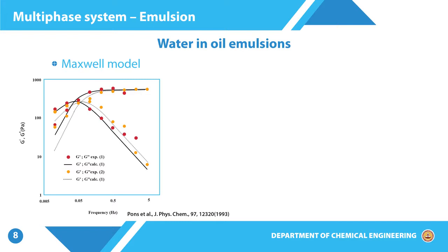In this case, frozen response means that basically droplets are unable to move. At most there is a small vibratory motion of the drops which is possible, and therefore, some amount of dissipation is there, but the overall cluster of drops and the network of drops remains intact and is not very mobile, giving us this glassy elastic response.